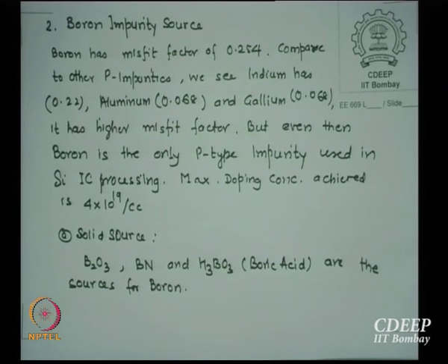Since this misfit factor is larger, what is the effect? Its solid solubility will be relatively smaller, so it is 4 into 10 to the power 19, in some cases maybe 5 into 10 to the power 19 per cc for boron. So P plus doping is always less than N plus doping, simply because the misfit factor of boron is larger than phosphorus or arsenic, of course, is the best. But arsenic, as this gentleman also said, is a slow diffuser. So in a shallow junction they are good, but if you are looking for deep junctions, phosphorus is the only solution.